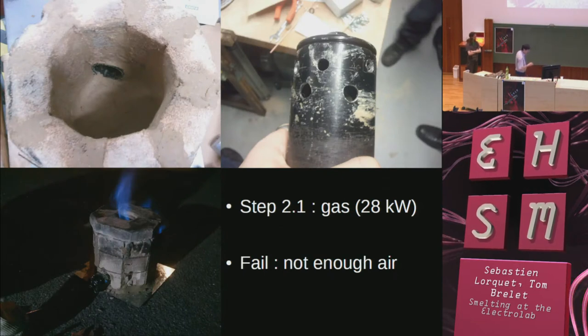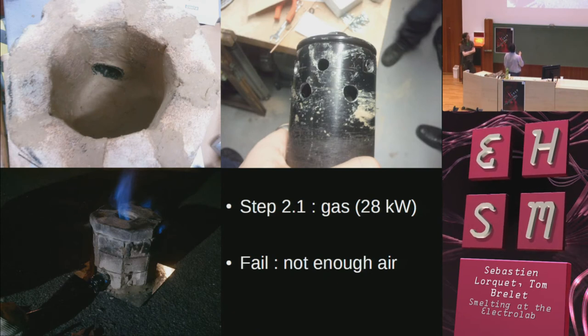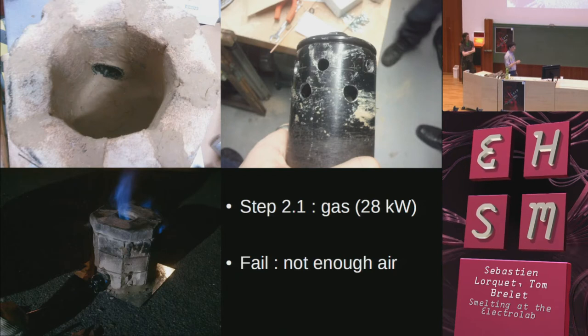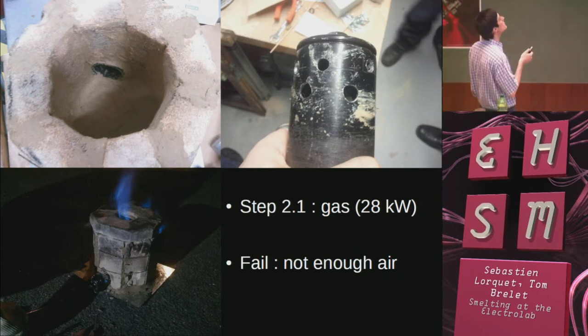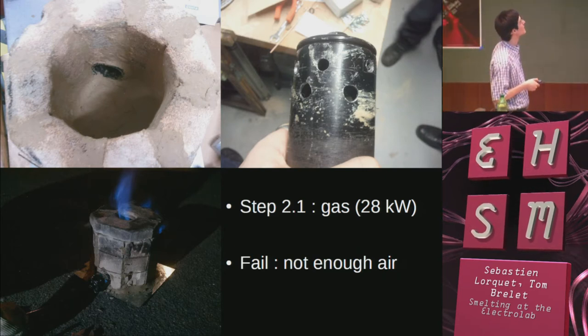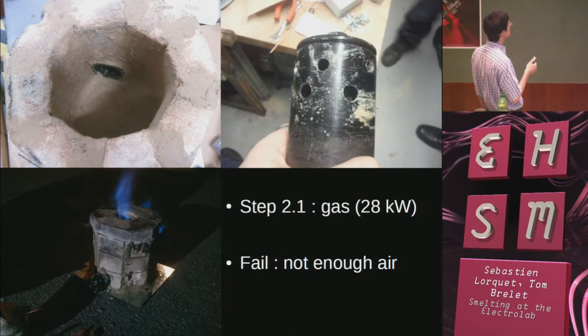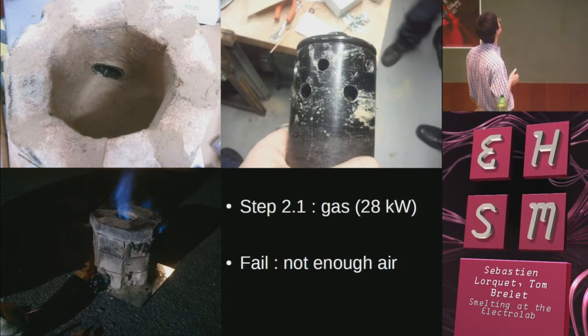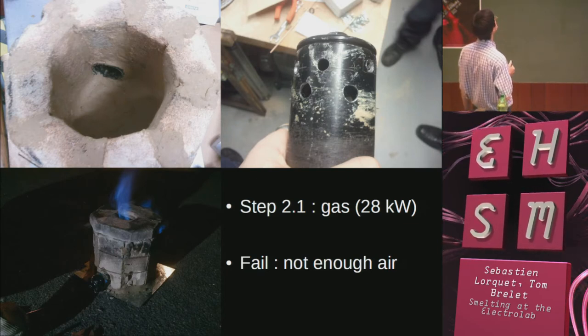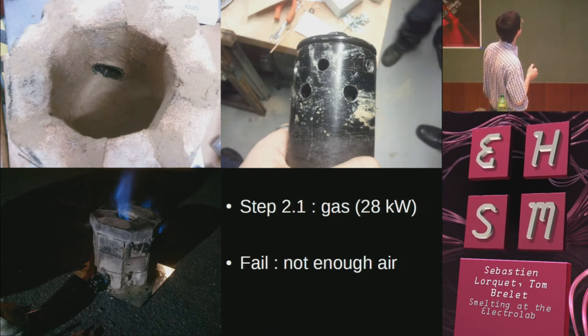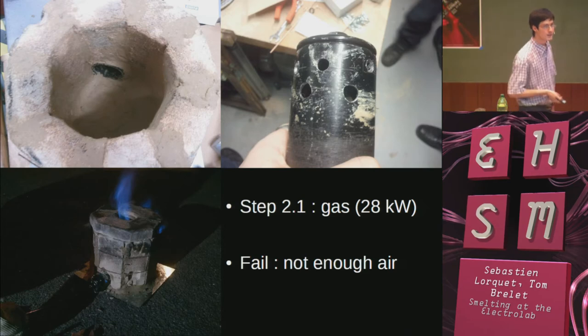So here it is. You can see the same structure, but here the clay is insulating everything, and here is a blower. It's a torch which is used in building construction to heat some parts. I don't know exactly. So we added holes with the goal of increasing the amount of air blown into the furnace, but it was a miserable failure. And here you can see only a very small blue flame, which is not hot, but it's blue because the whole furnace is just full of gas and there is no air inside, so nothing can burn.